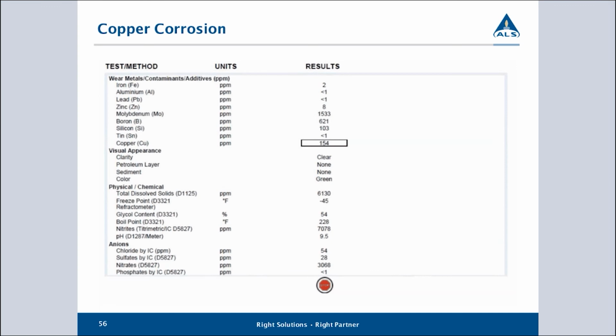And what I suspect has happened here is that the additive that is inhibiting copper corrosion has stopped working quite some time ago. And this is leading to the rapid increase in the copper corrosion that we see going on here. Again, the recommended action at this stage would be to flush the system completely and refill the coolant, and also make sure that we check what formulating coolant we are actually using here. This additive level just doesn't look typical for a coolant system, so we've probably got either mixtures going on here or something that has been heavily overdosed but is not correct for the application that this coolant is being used in.